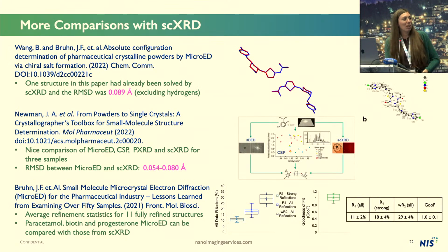And if you want more examples, in the paper with Biogen, here's an overlay of an X-ray structure that Bo determined and a microED structure I determined, and the RMSD between these two structures, they're nearly identical. It's very hard to see in this image, but the only real difference you'll see in the models is that the thermal ellipsoids from the microED structure are quite a bit larger, but the atomic positions are quite accurate.